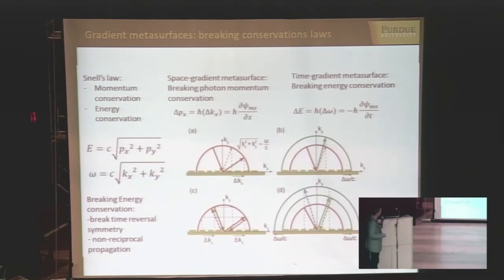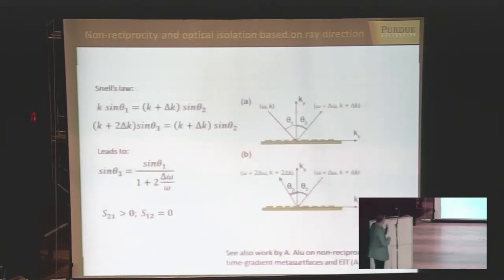However, it's still reciprocal. If you use a time-variant metasurface, when phase also varies in time, then you switch from one isofrequency surface to another after reflecting from such a metasurface. When you send light in the opposite direction, in this case, it would actually go in a different direction. So it's non-reciprocal light that you could obtain in this case.